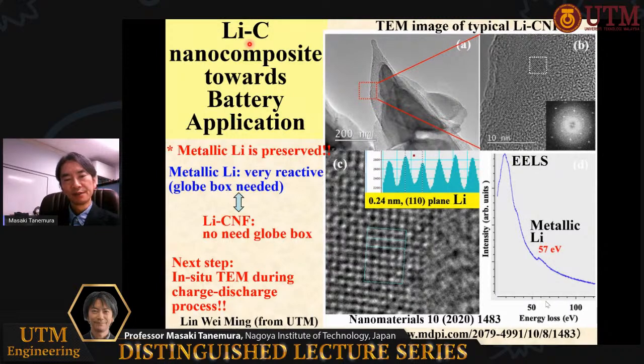Here, you see the conical structure, and this is the enlarged image of this red square. This is the atomic scale image of this white square. You see the regular array of white spots; they correspond to lithium atoms. This is the intensity line profile of the image corresponding to the lithium 110 plane. The presence of lithium is also confirmed by electron energy loss spectroscopy in TEM.